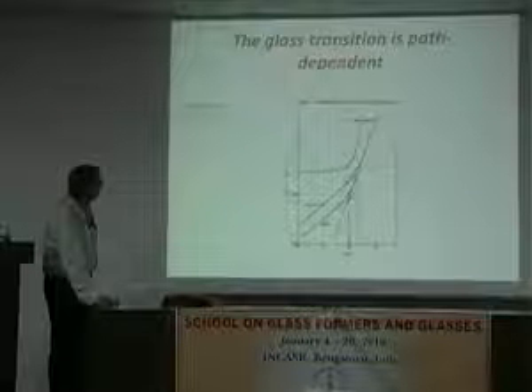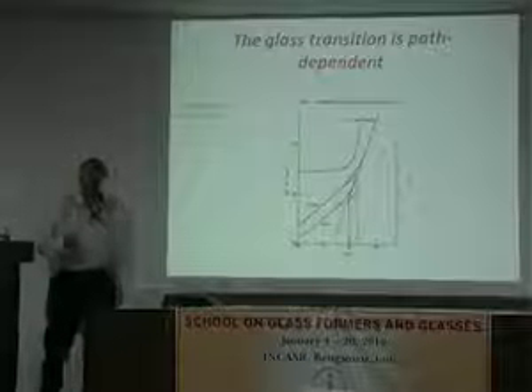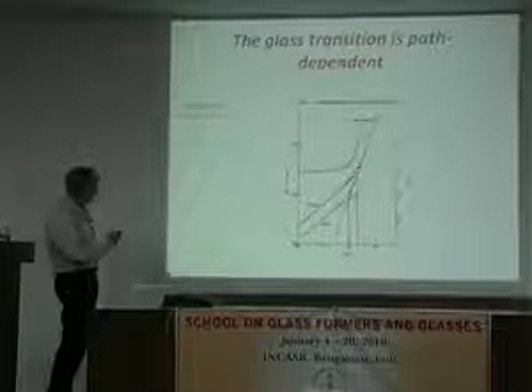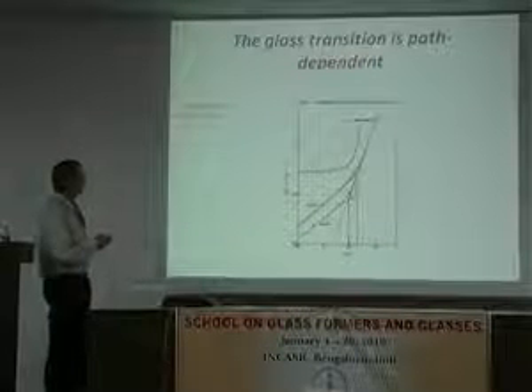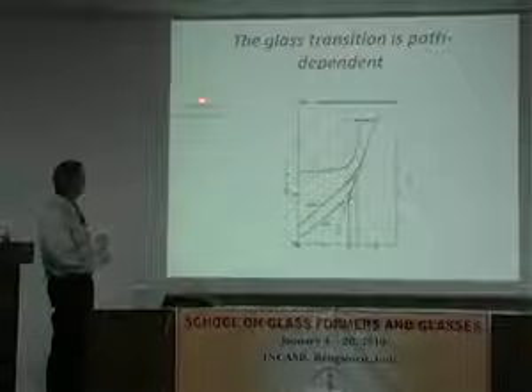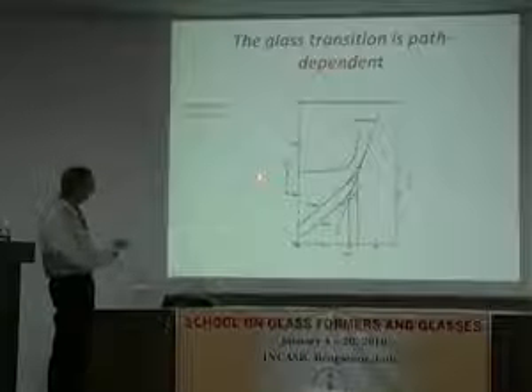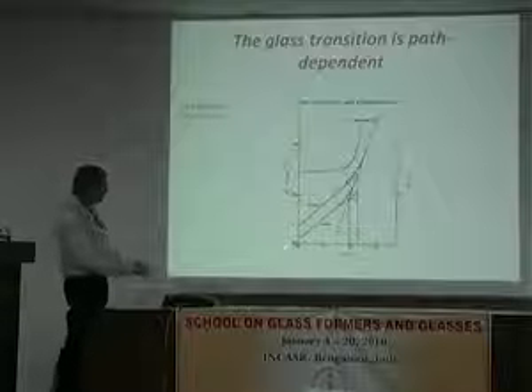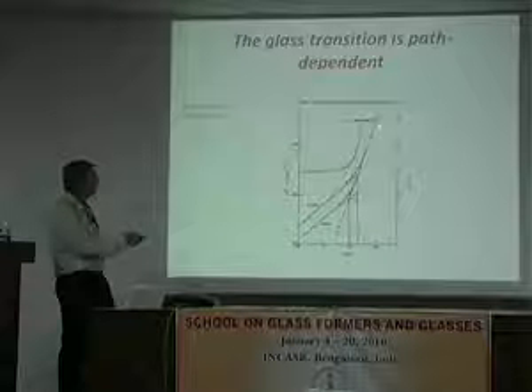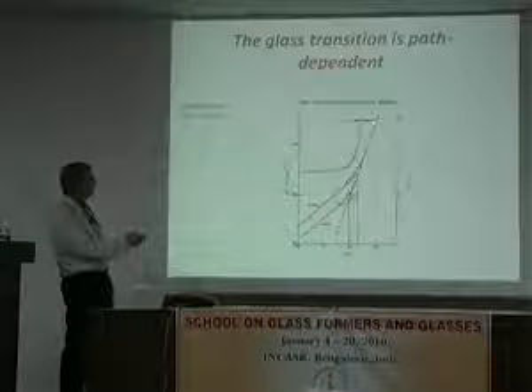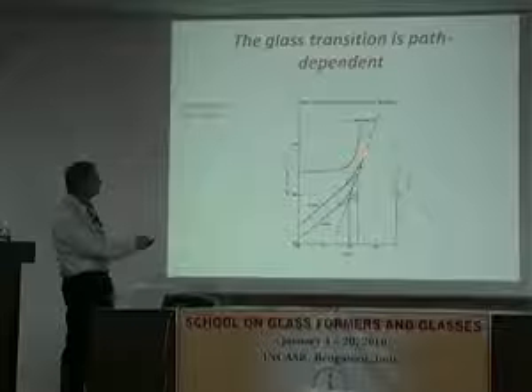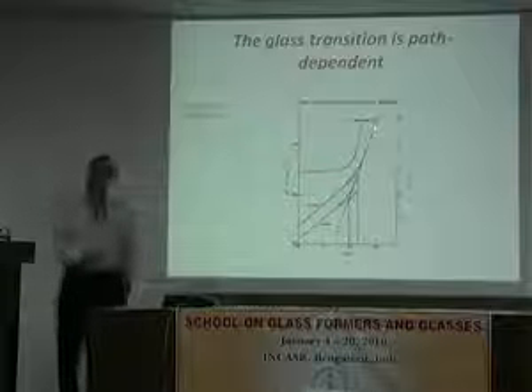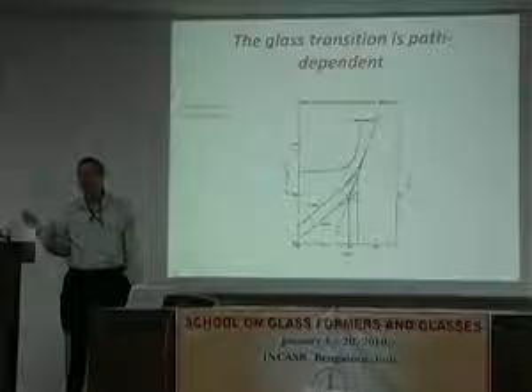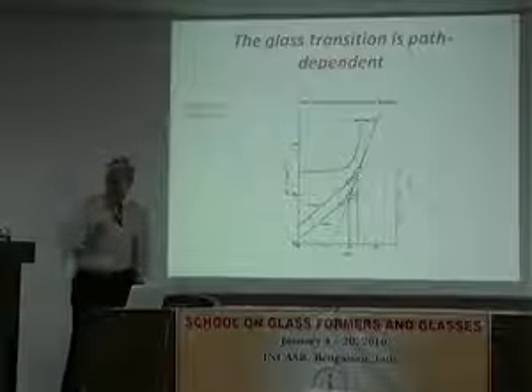So the path dependence, well, the easiest thing to see is, this is some data from Kovacs. And the glass transition depends on rate or time. So this is a plot of the specific volume as a function of temperature for a polymer, and I think it was polyvinyl acetate. But we start from the, well, in that material, we don't have a crystalline state, so we don't have a supercooled state. It's an equilibrium liquid state.